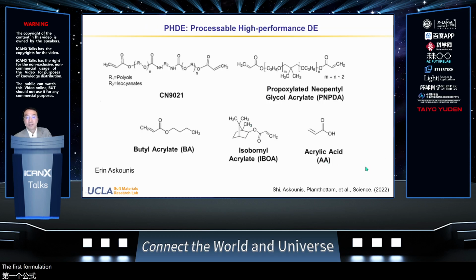The first formulations that we introduced recently replaced both the long chain diacrylate and the short chain diacrylate you see here. Erin in my group, who has graduated already, made hundreds of different formulations and settled on this system where we have these two different diacrylates, and also a butyl acrylate added to modify the viscoelasticity of the system, and isobornyl acrylate to enhance the tear strength of the resulting elastomer, and a small amount of acrylic acid.